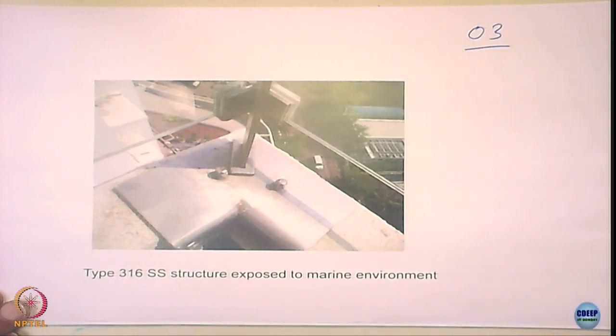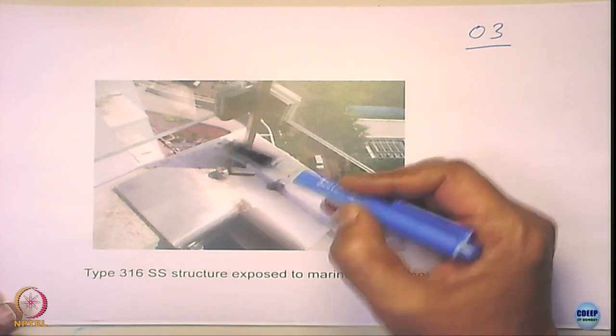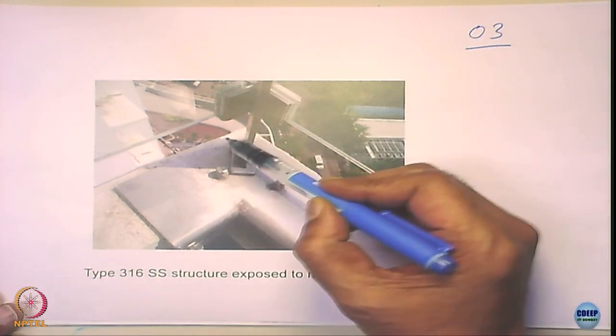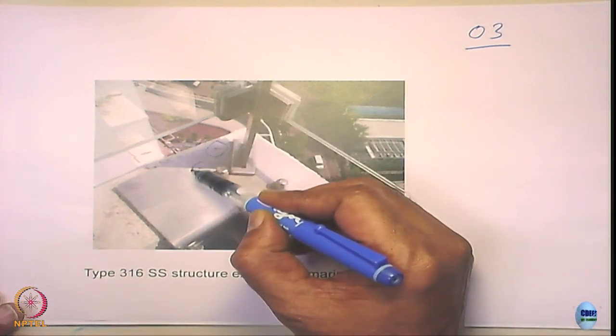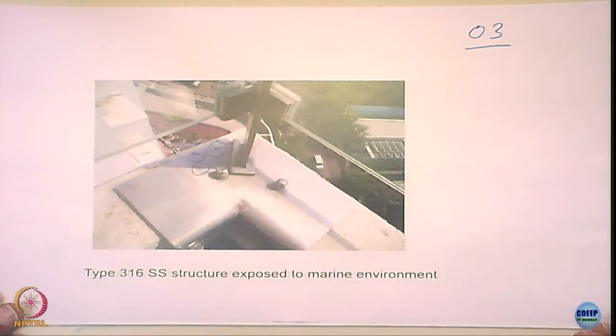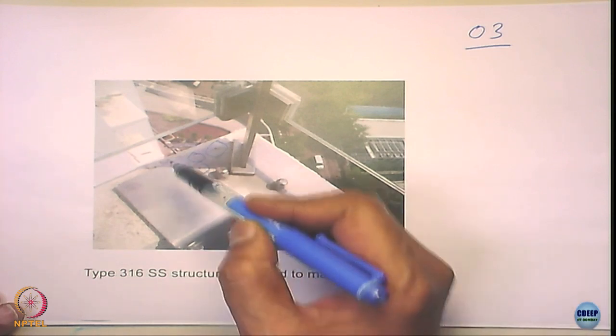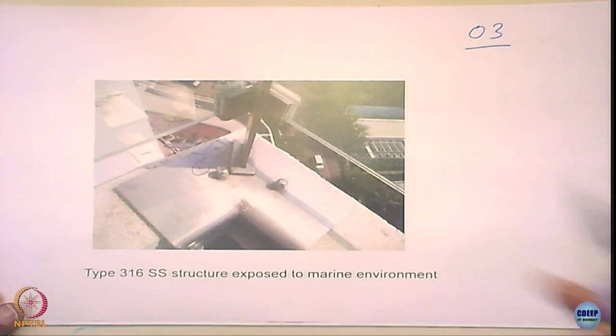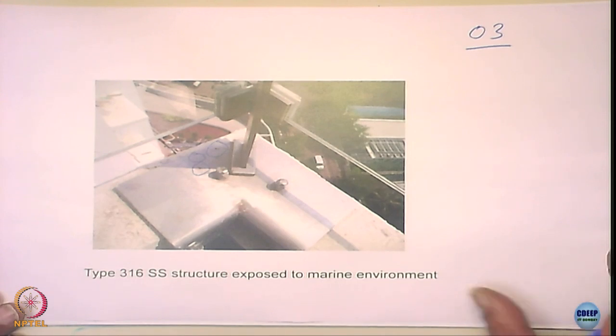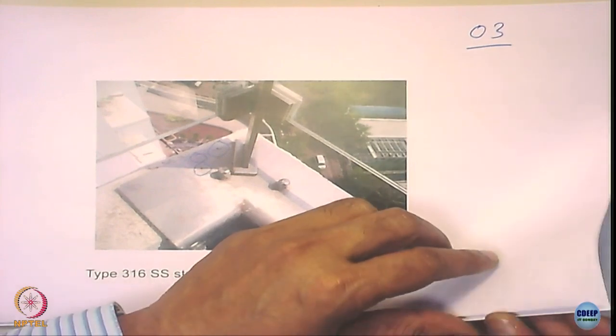And this is a civil engineering structure, in the same location. You would see here slightly better, I suppose. You are able to see a pit here, right? A pit around here, and a pit around here, and you see pits here, right? And of course, you have tiny pits somewhere around here. You can see lots of tiny pits which are visible to the naked eye, okay. And again, it is 316 stainless steel. You could see the pitting happening within 6 months to 1 year, okay.